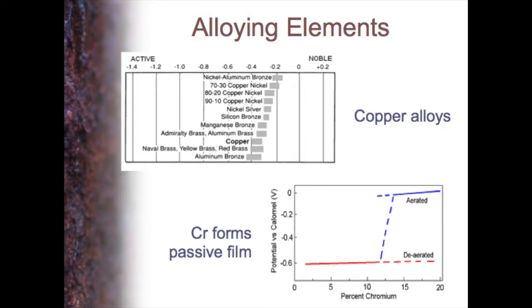From this work, if you have a passive alloy, you only get severe corrosion if the potential difference is around about half a volt. We said generally about 0.3 volts, but if it's a passive alloy it needs to be quite a bit higher than that.